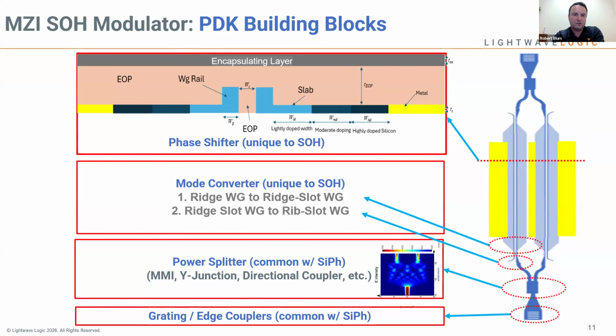But then what you need to do is convert the mode from the ridge to a ridge slot waveguide. And then after that, you want to convert it from that ridge slot waveguide to a rib slot waveguide, right, where you have a real rib. So there's a few mode converters, and then at the very top, basically in the middle of that, in the cross section across the Mach-Zehnder section, you basically have the phase shifter, where you have the electro-optic polymer, which is inside this slot, and obviously you have the silicon with different doping levels, from very highly doped, close to the metal, all the way to very lightly doped, when you're close to the mode, close to the slot.